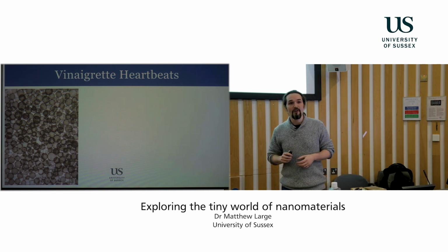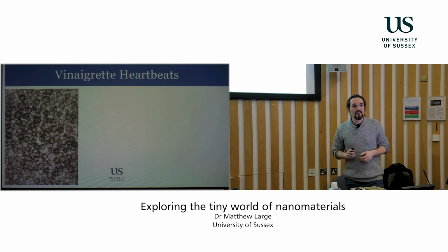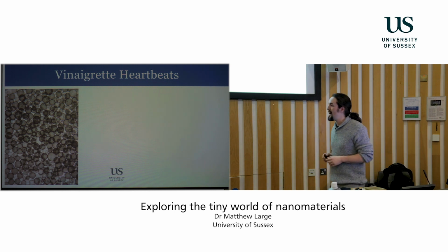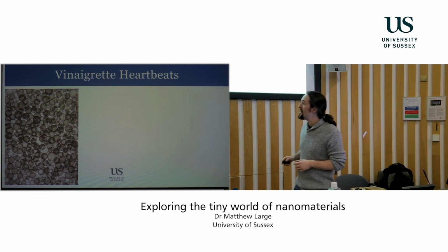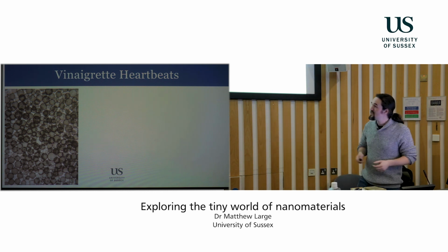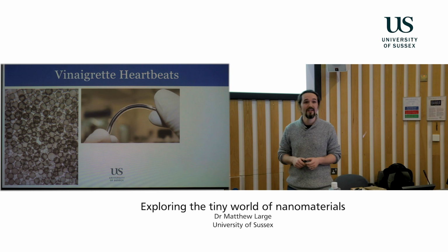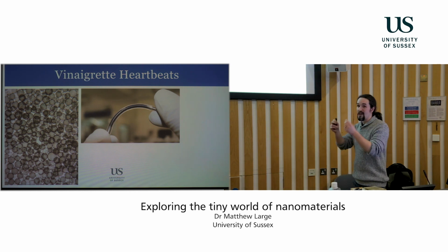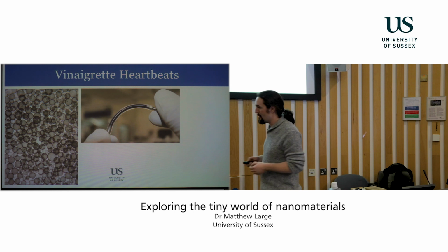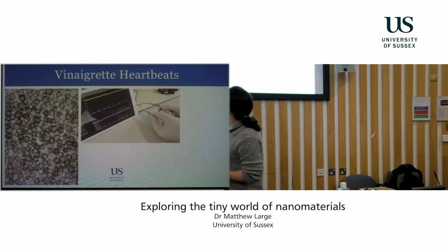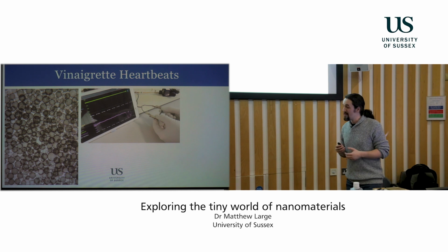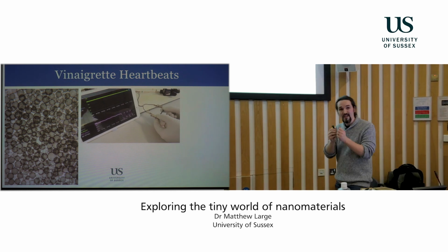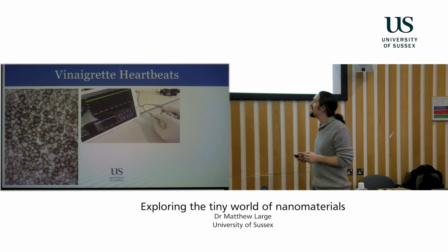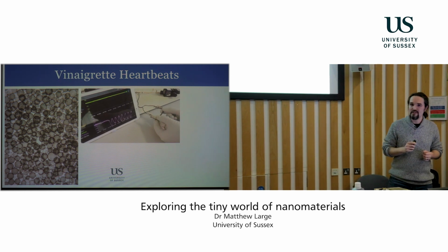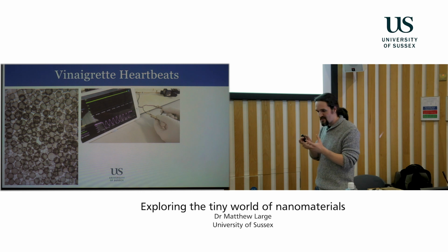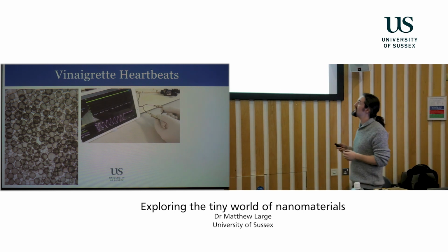Now, from what we know about graphene, it's very, very electrically conductive. So not only have we stabilized that emulsion of oil and water droplets, but we can make it conductive as well. So if we siphon that up into a pipe, for example, and apply some little electrical contacts, we can measure a current through it. And when we did this, what we found is that this system, this material, is immensely sensitive to very, very tiny stretches. In fact, this is the most sensitive way of sensing stretches using a liquid that exists.